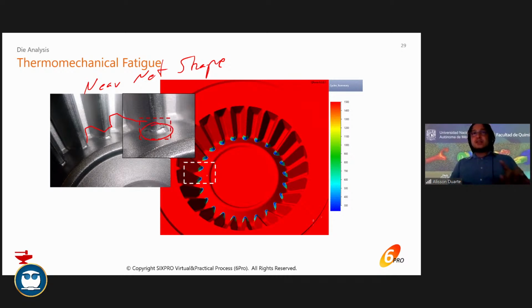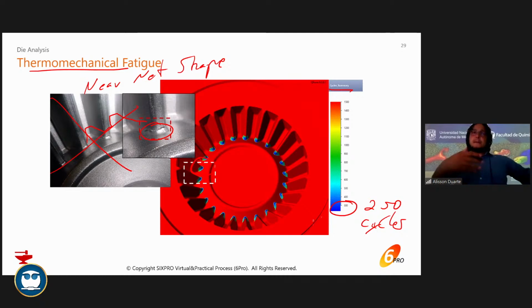And in the simulation, you can see that right in that area, it says, all right, around, let's say, 250 cycles after that, the die is going to break. The die is going to suffer a fatigue failure by thermomechanical fatigue. And it's possible to have this dimension in the simulation, like an average amount of parts that I can forge before break. But this is very, very critical. And sometimes the companies go there and try it by trial and error.